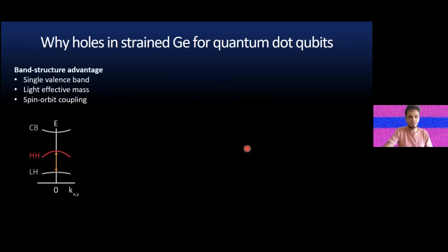Now, why are we so interested in holes for spin qubits? There are really, I would say, three main reasons. From a band structure perspective, you really have an advantage here. By working with strained heterostructures in germanium, what happens in the valence band is that you split the levels. So you're working with what in bulk we used to call heavy holes. But due to strain and confinement, it turns out that the effective mass is actually much lighter in this topmost band. That's very good if you think of quantum dots, because it means that the spacing between energy levels is larger, and so you can make quantum dots that are bigger.